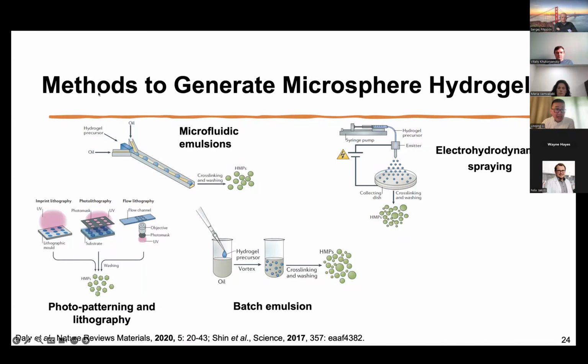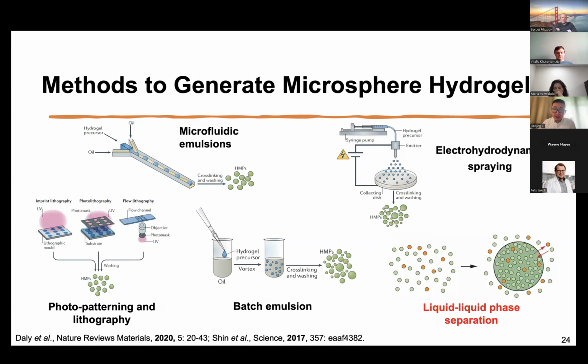However, when you're using microfluidic systems, the beauty is that you can control the particle size by the flow speed. But again, you have to go through purification steps and also annealing, which can be challenging and compromise the mechanical properties. And then for hydrodynamic spraying or lithography and patterning, you still require the setup, the equipment, and also expertise. So our lab is innovating to avoid using all that equipment and avoid using organic solvents, and we want to do everything in aqueous conditions.